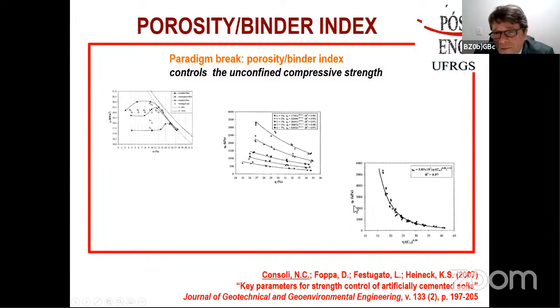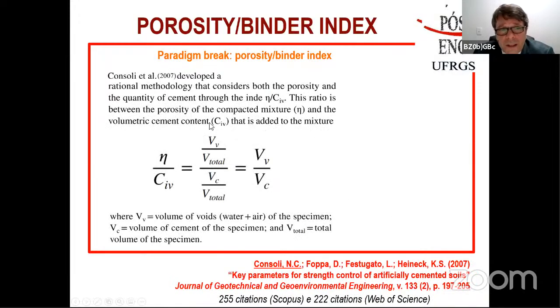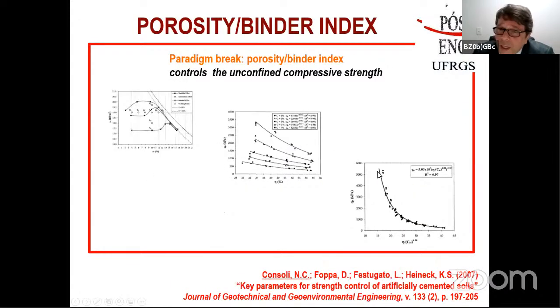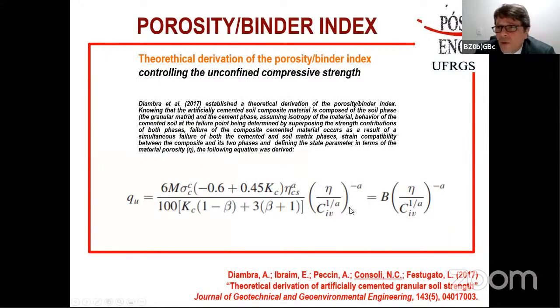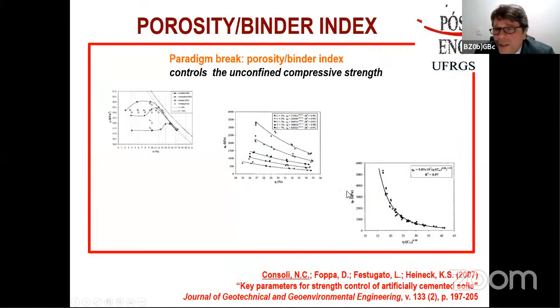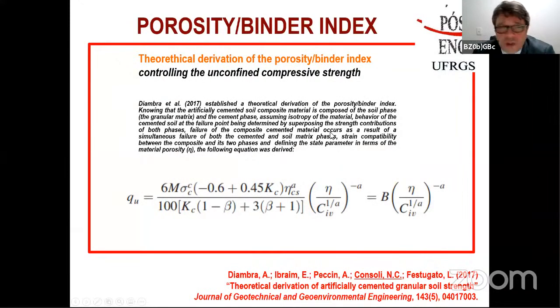But if we put the unconfined compressive strength from all these results versus this parameter here, we get a unique curve. Okay, so we are working in volume, which means that this parameter controls the unconfined compressive strength of this cemented soil with Portland cement in this case. Up to this moment in 2017, we had seen this concept in the lab and also from specimens taken from the field. But we developed an analytical solution showing that this is true in 2017, after a period that I was in Bristol working with Professor Diambra and Professor Ibraim.